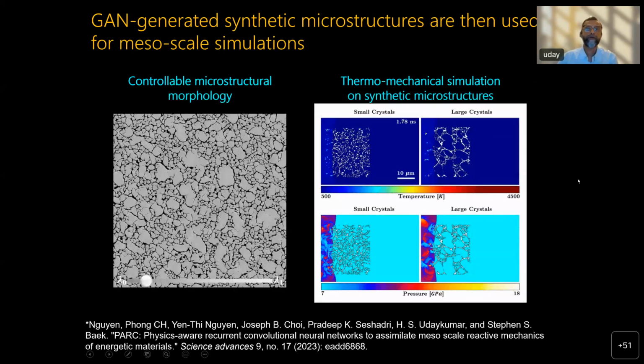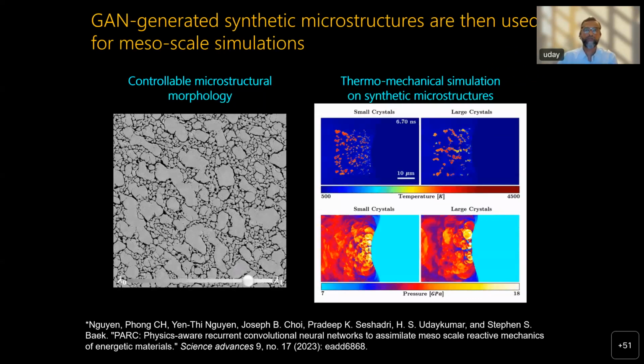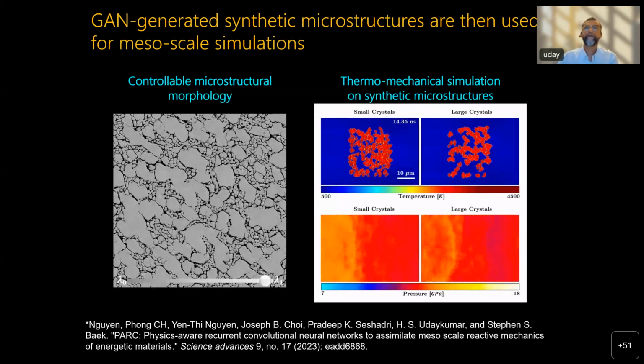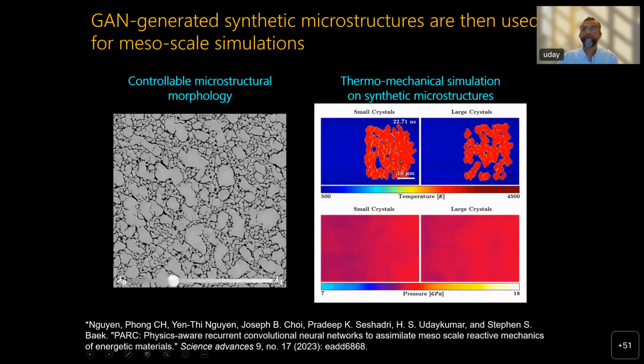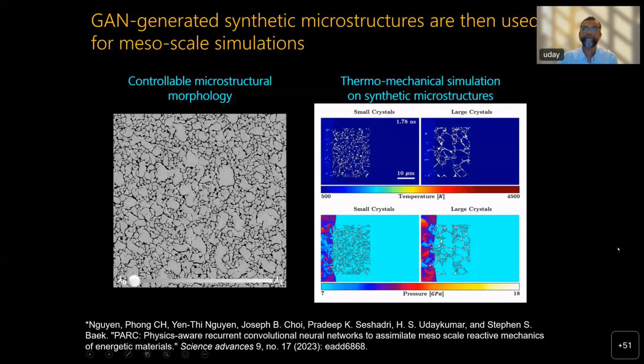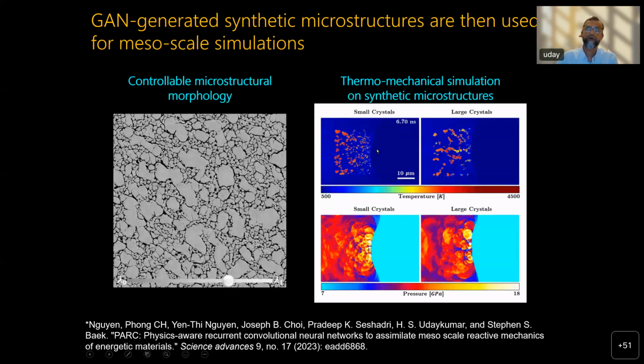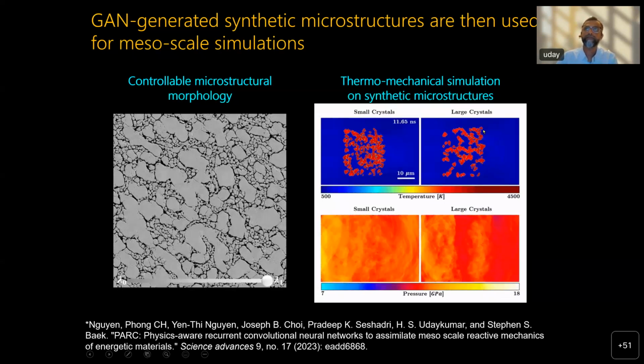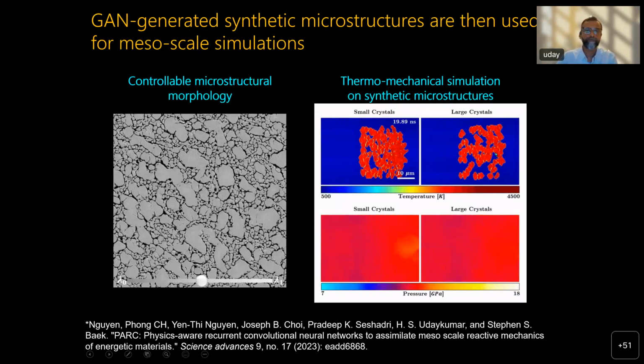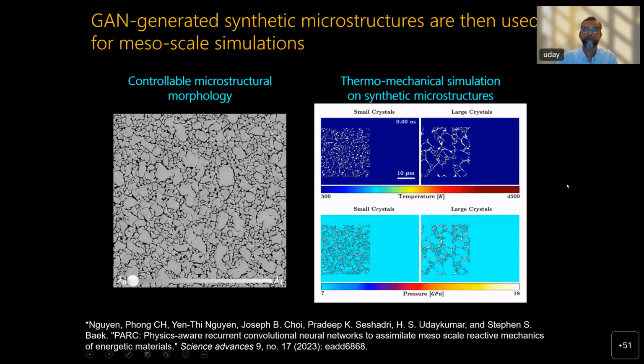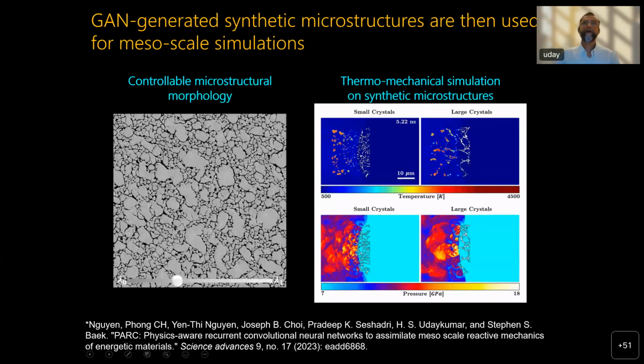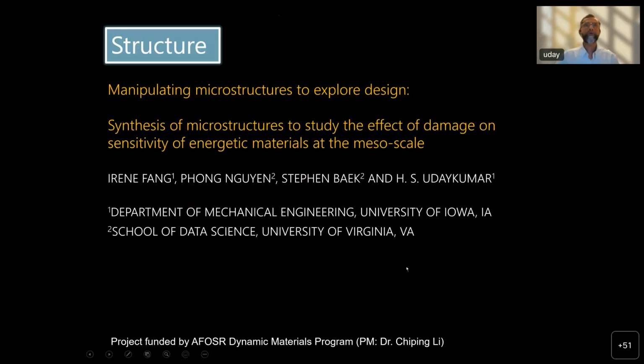And then, of course, finally, we use these microstructures, the synthetic ones, and look at the shock response of it in simulation. So this is for small crystals and for large crystals, and you can see that the growth rate of hotspots is very different in the two of them. So that's the facility. Now we're also doing other things.